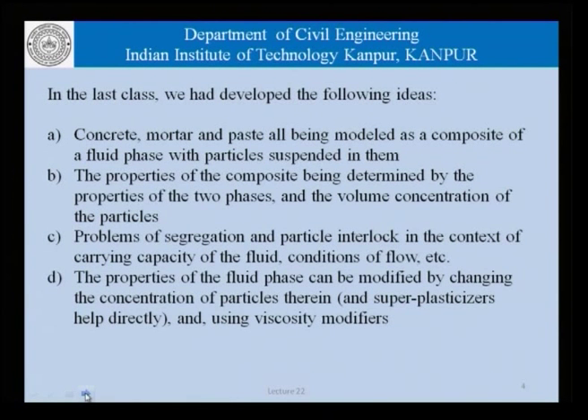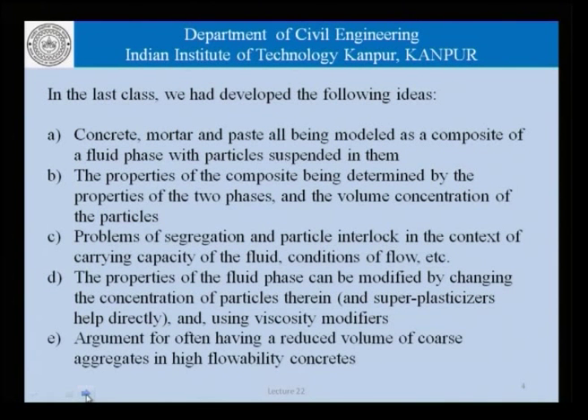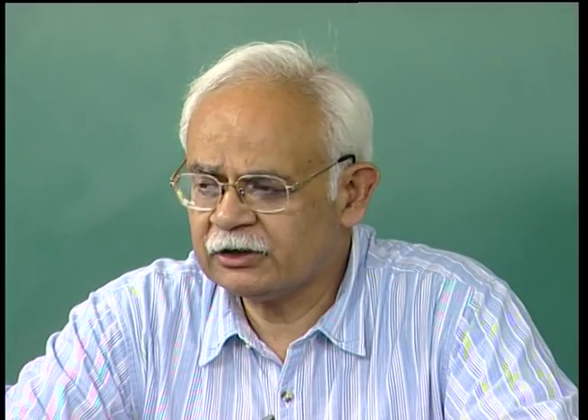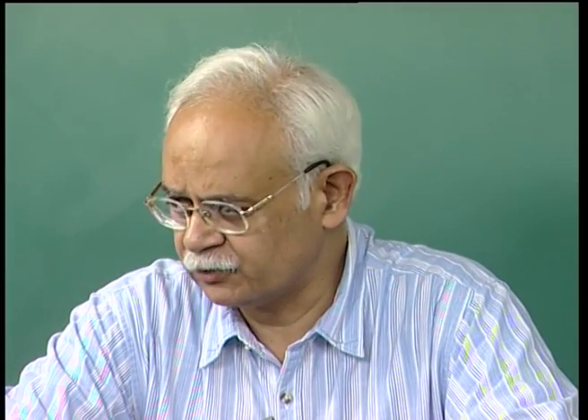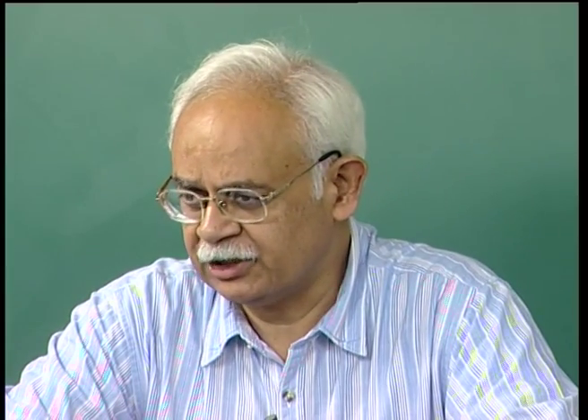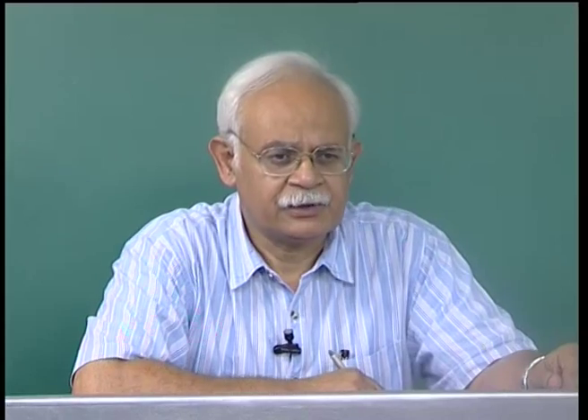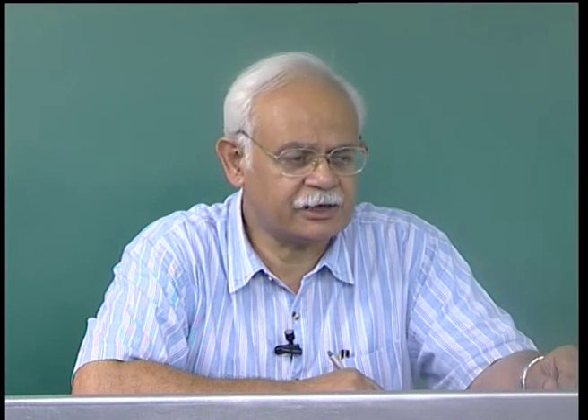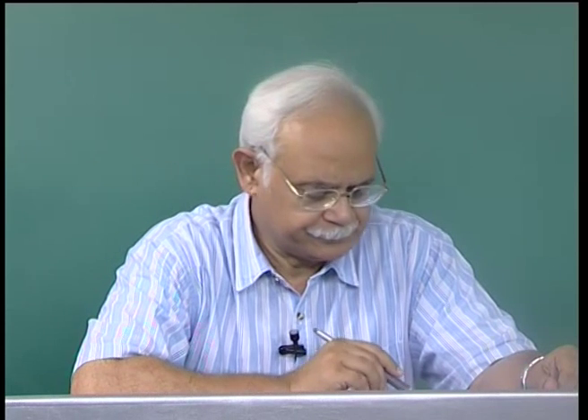We had talked about the properties of the fluid phase, which can be modified by changing the concentration of particles therein, and superplasticizers help us directly in that context, and also using viscosity modifiers. We had also built an argument for having a reduced volume of coarse aggregates in high flowability concretes. In fact, there was a slide, if you would remember, where we had said that depending on the concentration of reinforcement or the complexity of the shape in which the concrete has to be cast, the maximum volume of coarse aggregate in the concrete can be limited or needs to be limited.